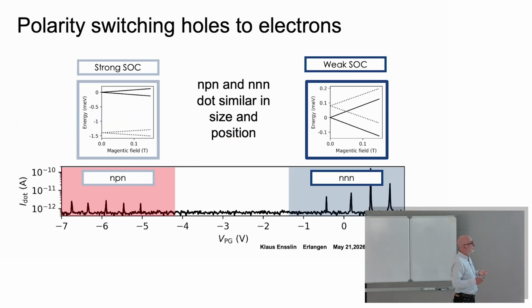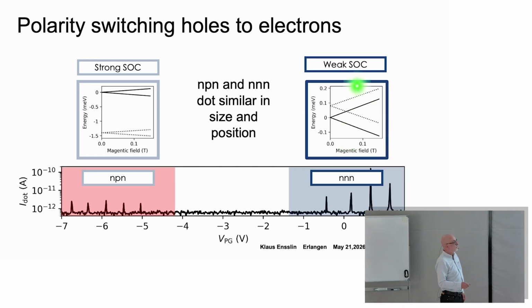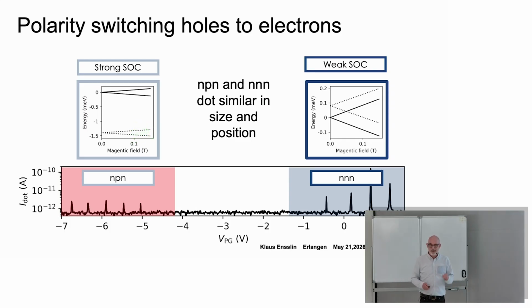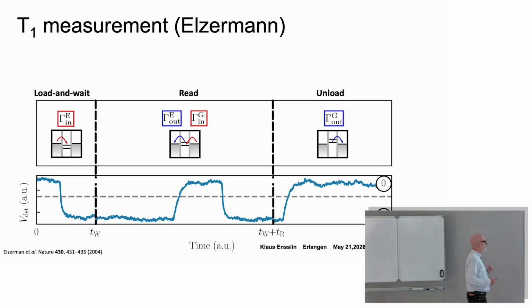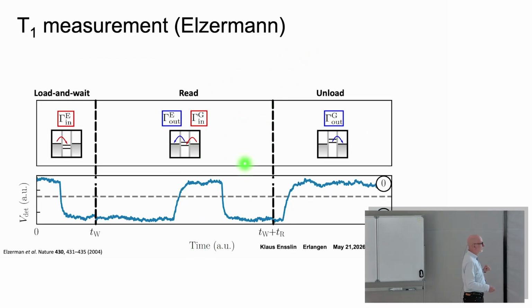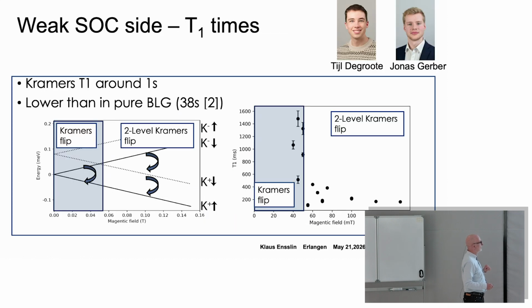And now you can ask yourself, what happens to the lifetime, right? I showed you lifetimes for this system. Here we had the intrinsic spin-orbit interaction, about 80 microelectron volts. Now I told you we can raise that to about 1.5 millivolts. So the energy spectrum without TMD looks like that. With TMD, it looks like that. So now we measure the time it takes to decay here and the time it takes to decay here. So does the spin-orbit interaction do anything to your spin valley qubit? And I show you the results directly. That's the same Elzermann readout that we are using. And we come directly to the results.